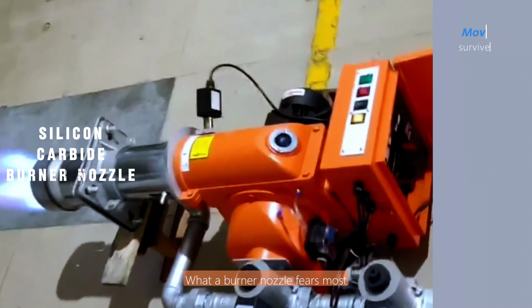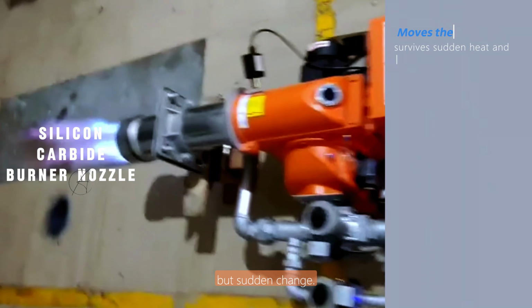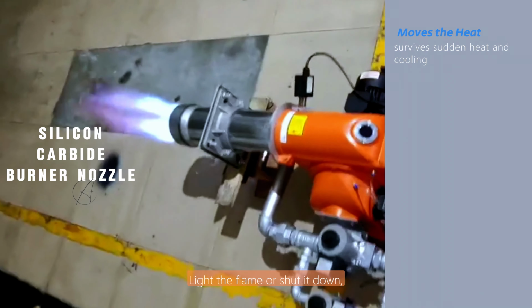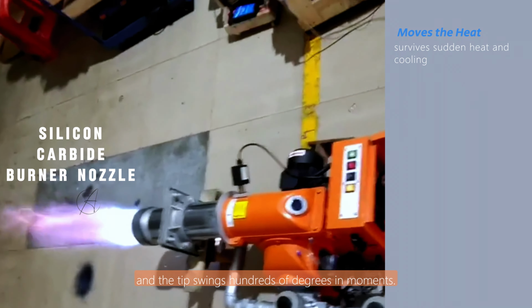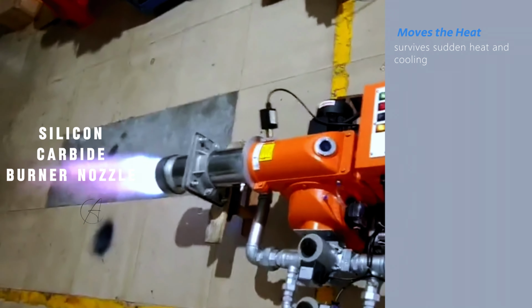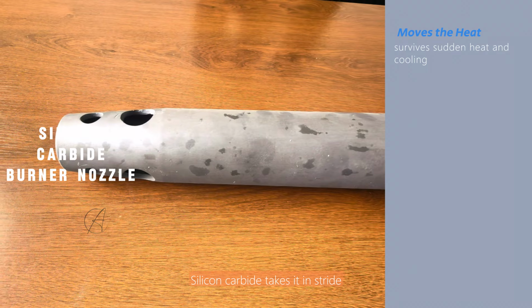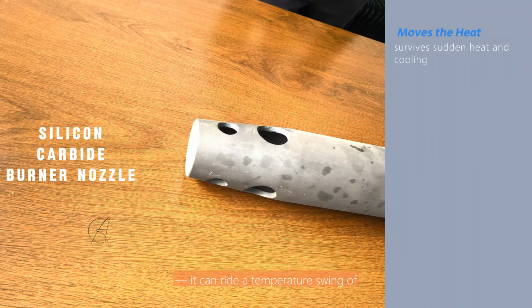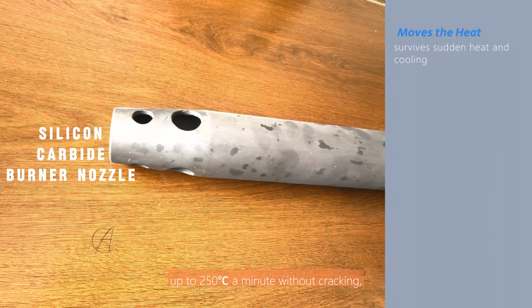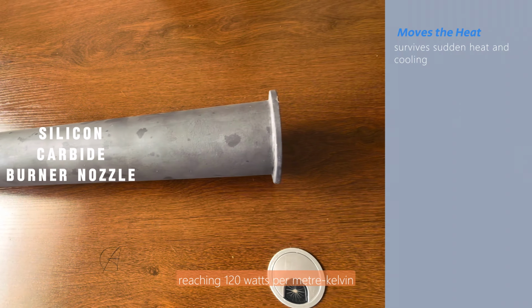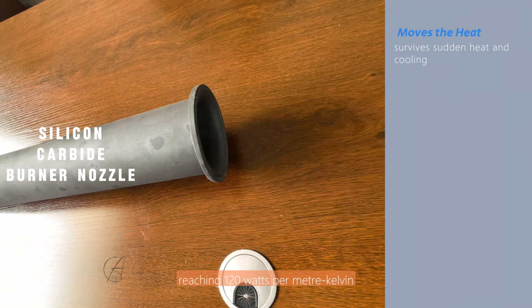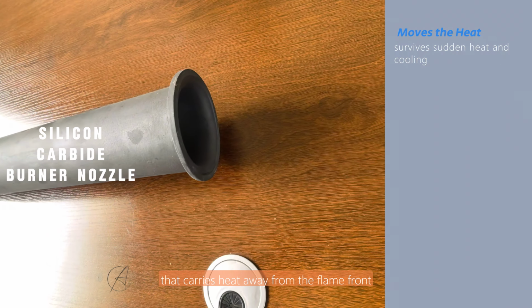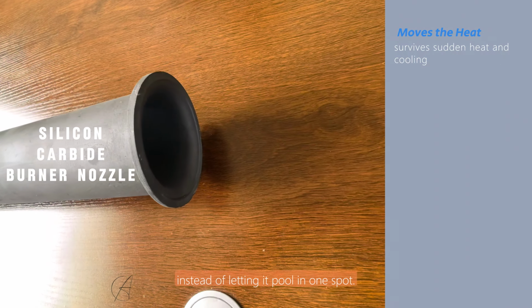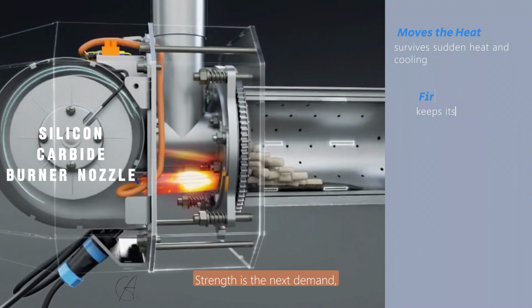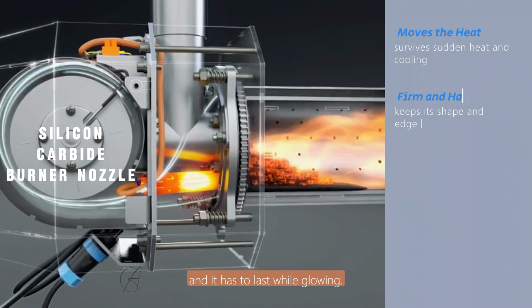What a burner nozzle fears most is not heat itself but sudden change. Light the flame or shut it down, and the tip swings hundreds of degrees in moments. Silicon carbide takes it in stride. It can ride a temperature swing of up to 250 degrees a minute without cracking, helped by a thermal conductivity reaching 120 watts per meter Kelvin that carries heat away from the flame front instead of letting it pool in one spot.